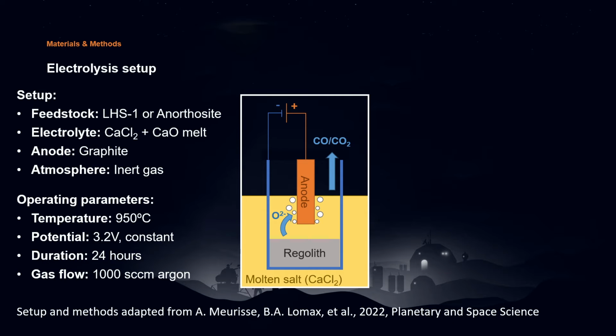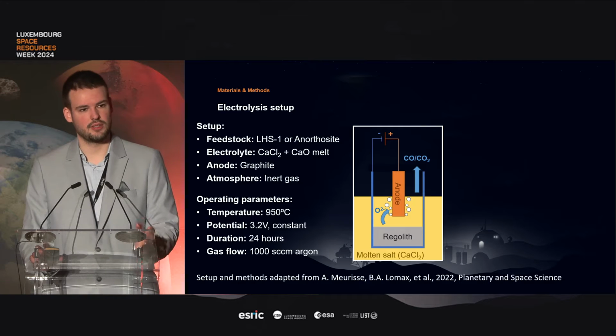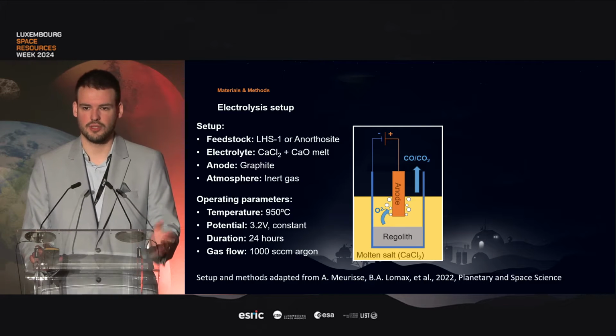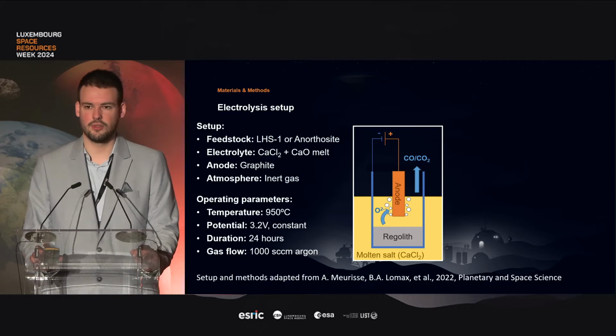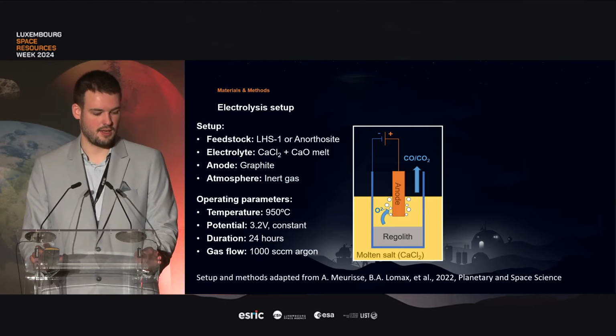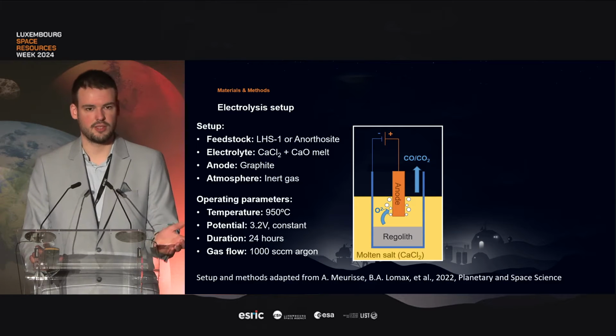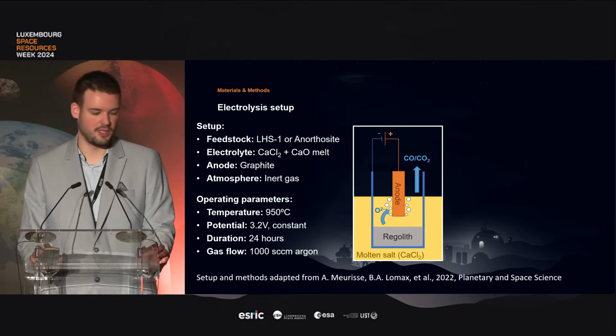We did a series of electrolysis experiments using a setup very close to what has already been described in the literature. So just to go through it quickly, the regolith simulant we're using is LHS1 on one side, and we also did some tests with pure anorthosite, which is one of the constituents of LHS1. The regolith gets pressed into a pellet that is introduced into a bath of molten calcium chloride. We apply then a fixed potential to this system, and the oxygen present in the regolith evolves through the salt and is released as, in this case, carbon monoxide and carbon dioxide at the carbon anode.